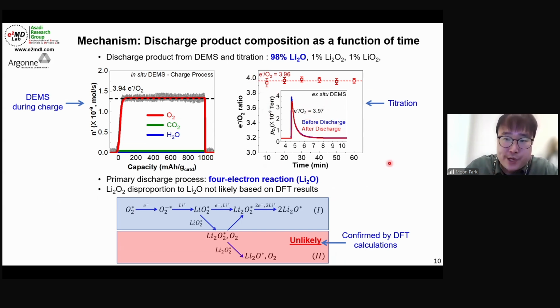And we also did the titration, as shown before. The titration can quantify the amount of lithia. And we got almost 100% lithia, 98%. From those numbers we can calculate, and then we know the discharge capacity. We can calculate 3.96 electrons transferred during the discharge of the cell. So from this result, we could learn that at room temperature, with a very specific optimized condition, we can make a 4-electron reaction and form lithia as the major final discharge product.